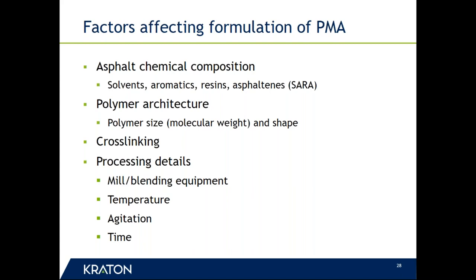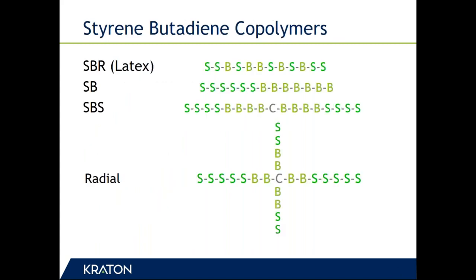Again, asphalt binders are not all the same by any means chemically. So that chemical composition in combination with the polymer architecture are the primary things that affect the formulation. How you cross-link them or connect them once they're in place is another thing, and there's a variety of ways of doing that during the production of the polymer modified asphalt binder. And then details during processing, such as the equipment, temperature, agitation, the amount of time used, affect the formulation of the polymer asphalt. Different types of styrene butadiene copolymers exist.